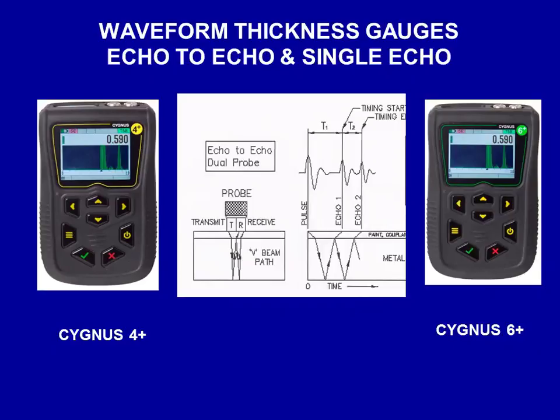The other thing with echo to echo is that since you're still only looking from when the clock turns on and it's timing, you're still only looking at a single echo. So if you have crap in the steel, you can get false readings on the echo to echo gauges as well. But we put them in our gauges.